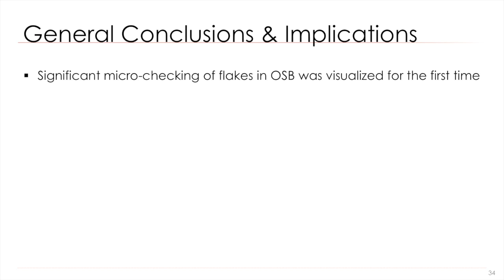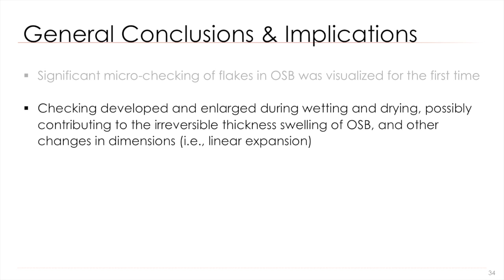So now I would like to finish up this presentation pointing out some general conclusions and implications from this study. For the first time, significant microchecking of flakes in OSB was visualized. So from one of the first slides where I mentioned the factors in the literature that affect swelling of OSB, now it's possible to suggest that checking can also cause change in dimensions, such as in thickness swelling and linear expansion.